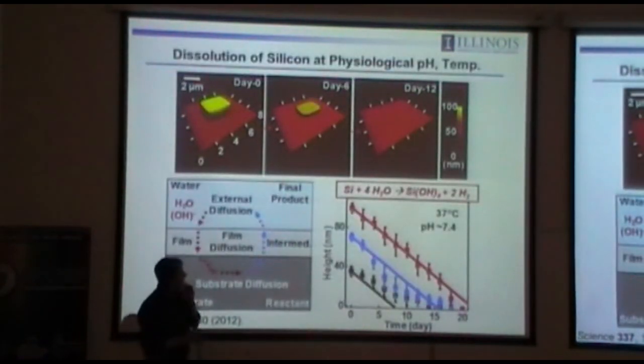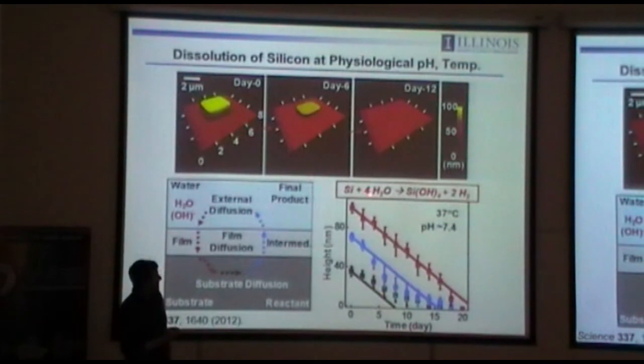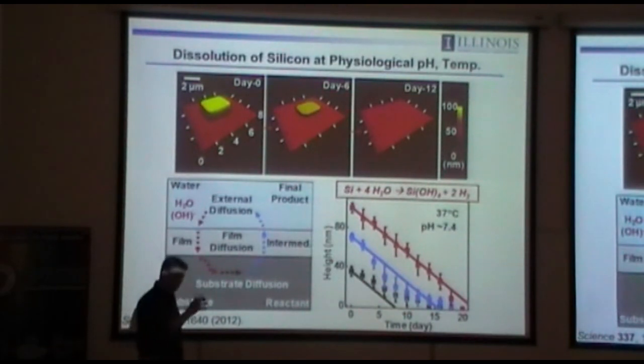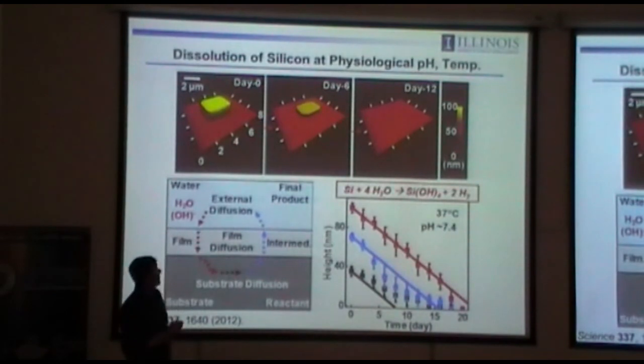In fact, silicon will undergo hydrolysis with water to form silicic acid at rates that are small but appreciable at physiological conditions. So we get about 37 degrees, 7.4 in terms of pH, that's close to what blood is. Silicon will dissolve at the rate of about 2 nanometers per day. So you put a silicon wafer in this kind of condition, you never notice anything is happening. But if you go back to this very thin silicon that we like to use for flexible electronics, silicon is completely gone in just a few weeks.